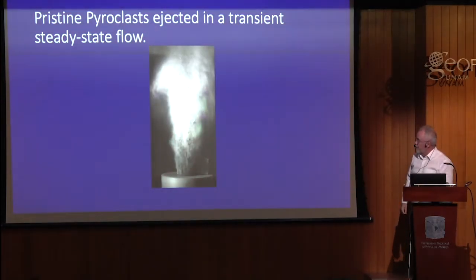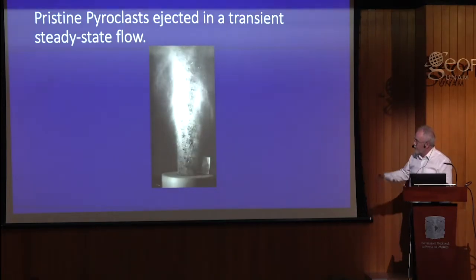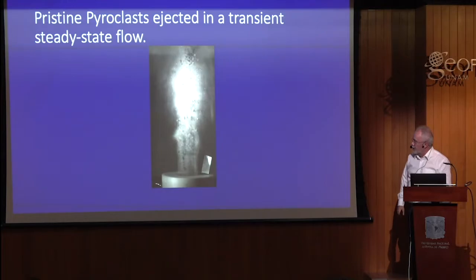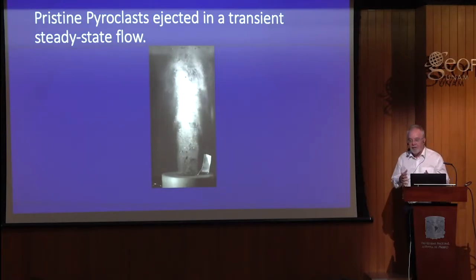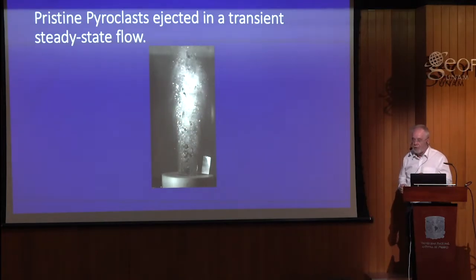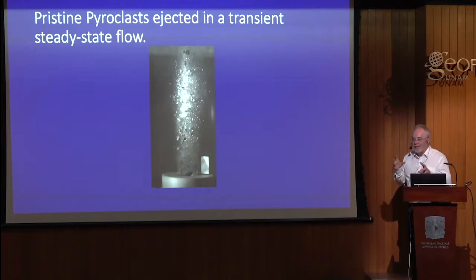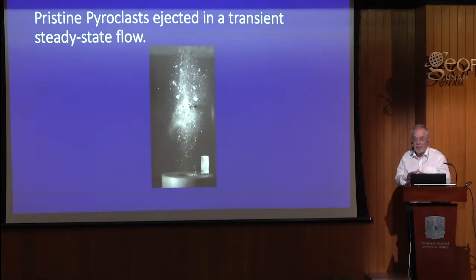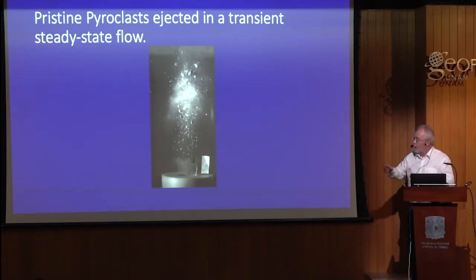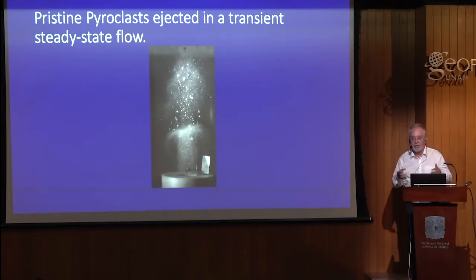And here comes the ash and the lapilli. Okay, so you see we can do high-speed videos and we can watch what is essentially a steady state flow for a few microseconds, a few milliseconds, okay? So although we call this an explosion, by going to high-speed cameras, we can control, we can tame this, we can monitor this, we can measure the velocity, we can measure the deceleration, we can even track individual particle trajectories,